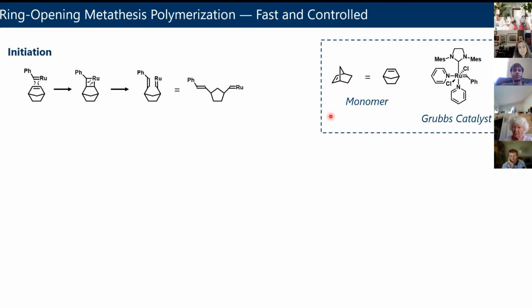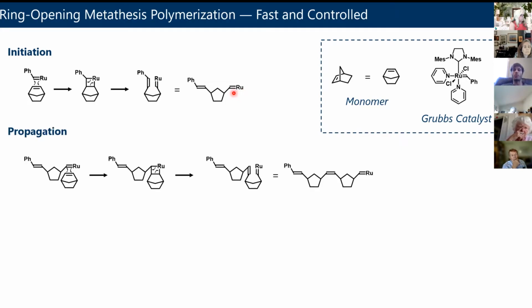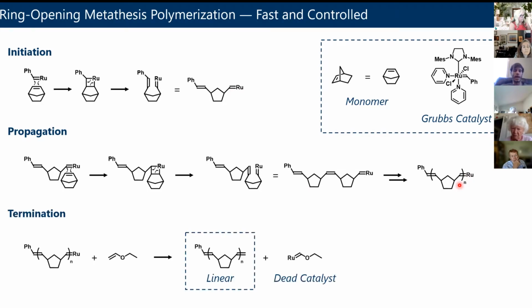And the mechanism is as follows. If you're interested, the ruthenium with that double bond to one of the ligands can do a 2+2 cycloaddition and then revert in the opposite way. And if we redraw this, you can see it split open one of the rings. And it's got an active ruthenium center on one side. This thing can then react in the same way with another monomer, where now you've got two repeats with an active ruthenium center on the end. And this process can repeat over and over and over again to build up a polymer with many repeat units. And then when you expose this after the reaction to something like ethyl vinyl ether, which is a liquid, you just squirt it into the reaction, you cleave off this active ruthenium center, you cap it with a carbon, and the polymer chain is done growing.